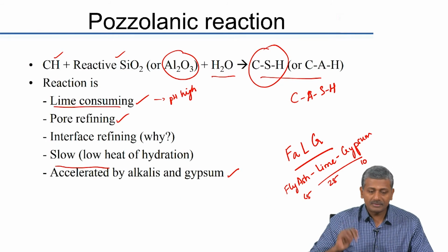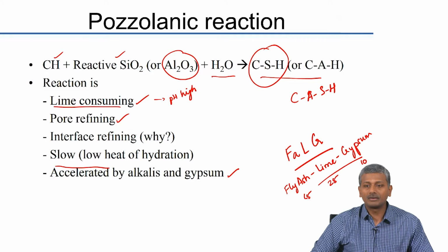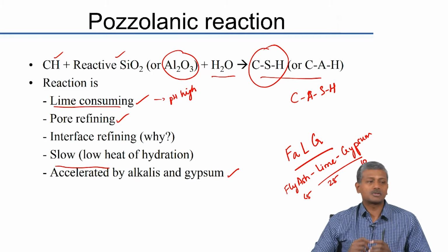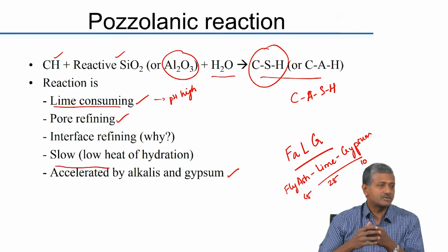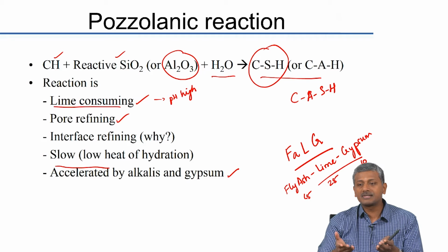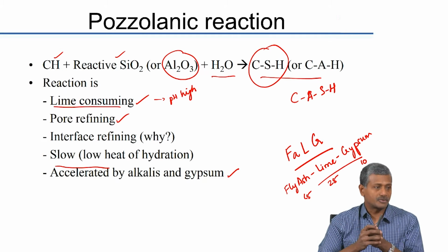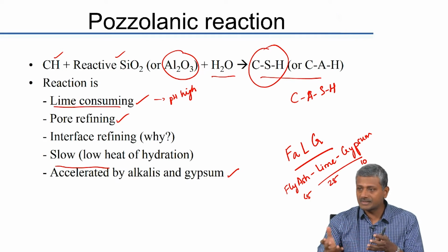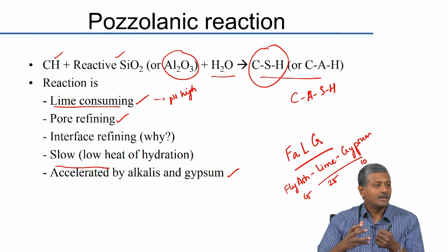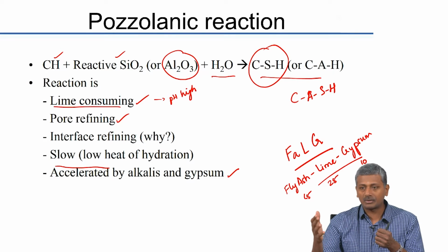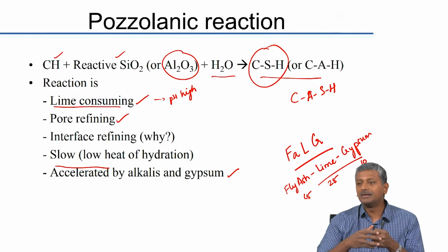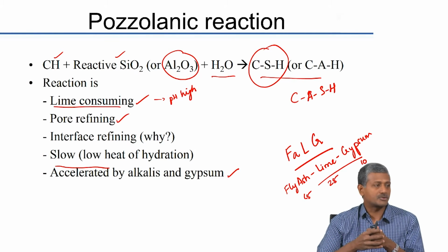The reason is this reaction here, the Pozzolanic reaction. Now, you know that when cement hydrates, it produces a lot of lime. Calcium hydroxide is aplenty because primarily it is C3S in cement, and you know that C3S produces very large amounts of calcium hydroxide. So, this calcium hydroxide provides a nice alkaline buffer, okay. It provides a good buffer, and when an external chemical like a chloride or a sulphate or a carbon dioxide enters the cement, it starts first reacting with the calcium hydroxide.